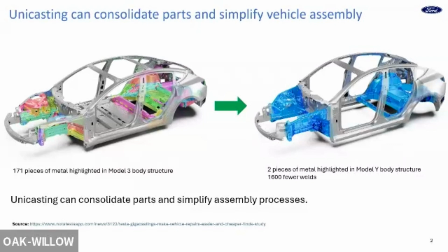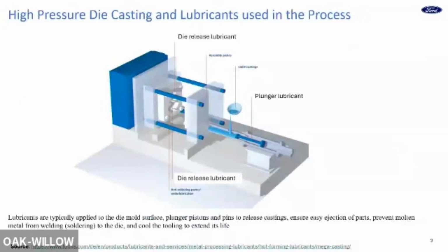And with these reduced parts, the joining can also be reduced significantly. For example, here there are 1,600 fewer welds. Unicasting can be made by high pressure die casting technology. Normally the molten liquid is injected into the chamber and it solidifies quickly, taking a few seconds to make one casting. The liquid metal has a temperature of about 700 degrees C, and it can